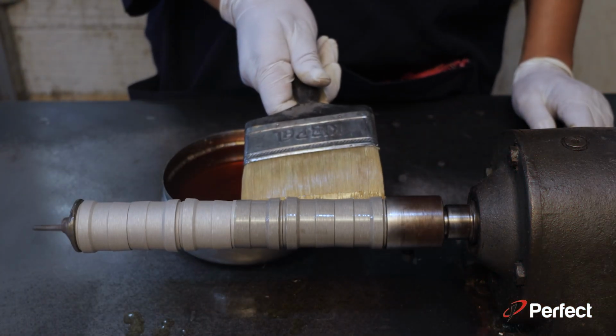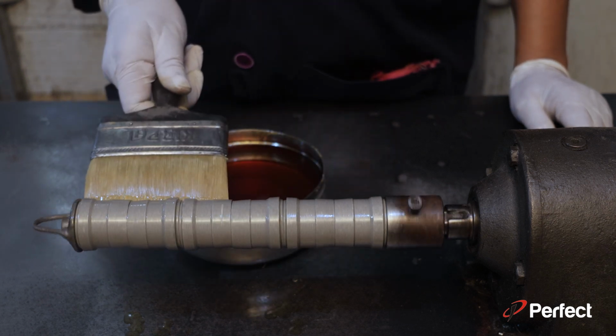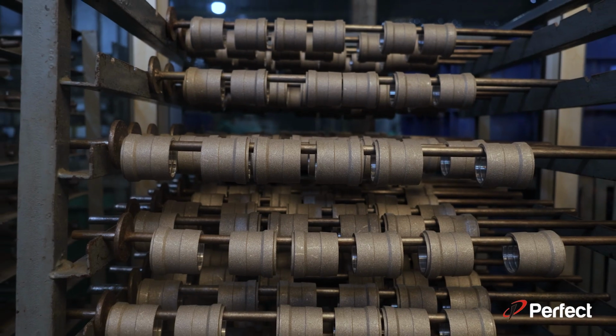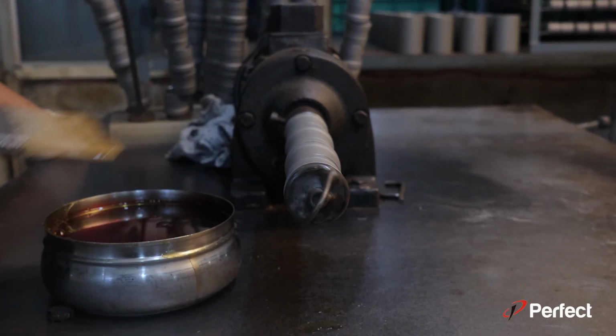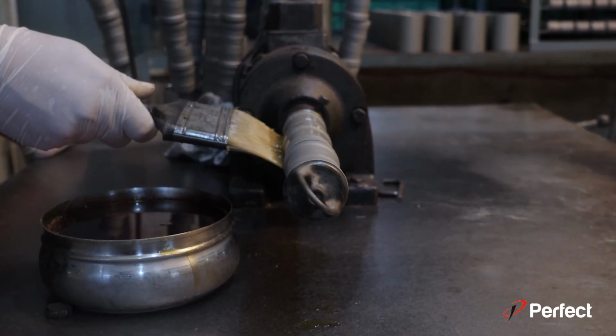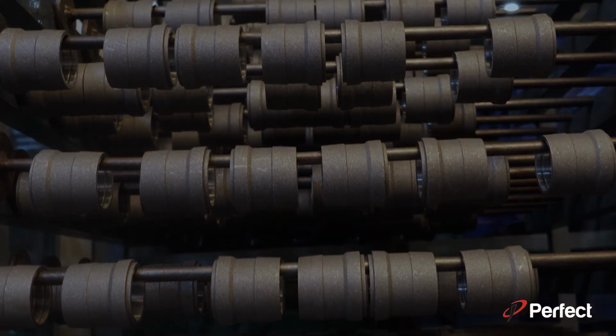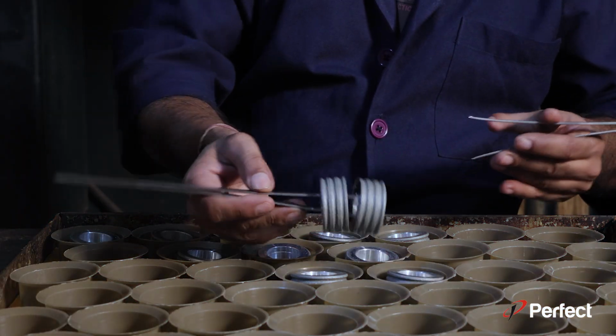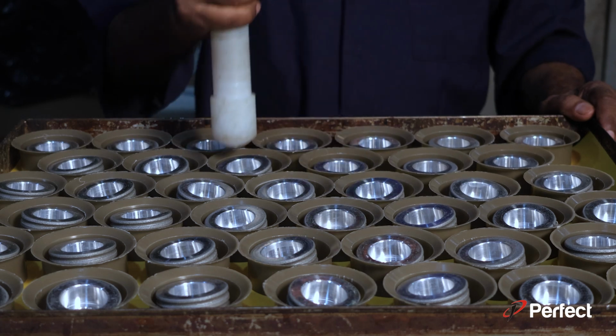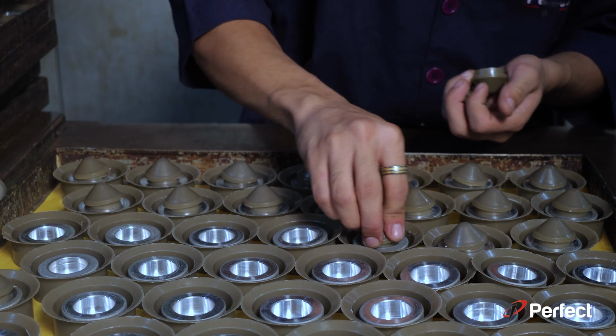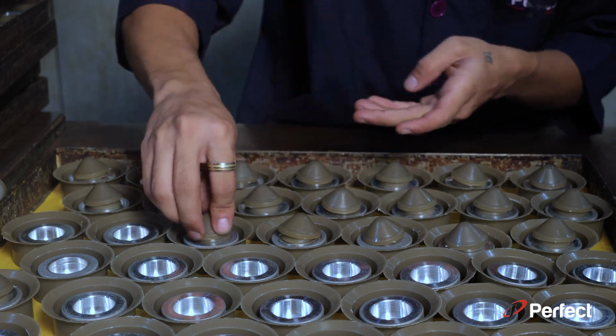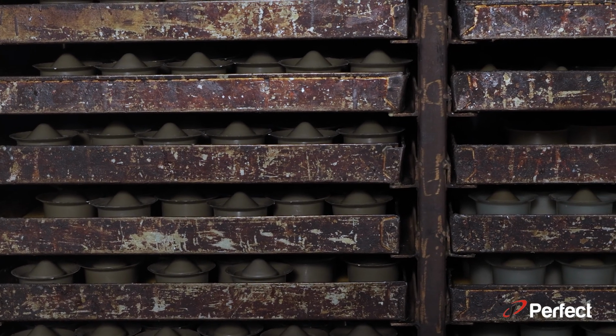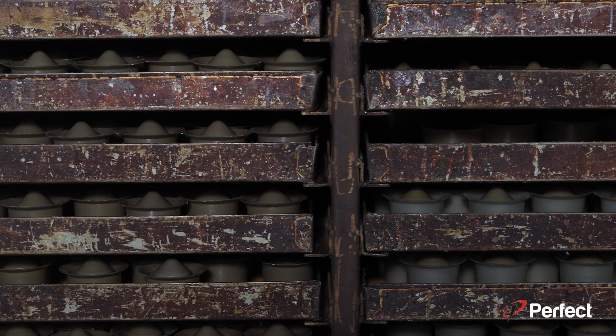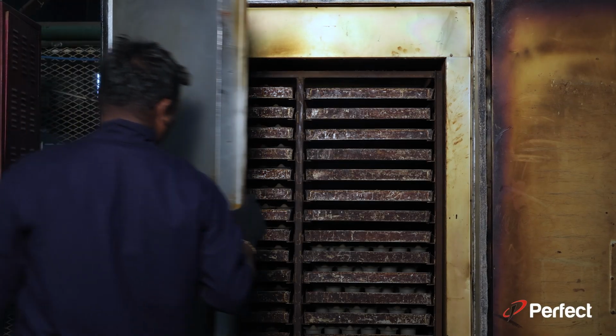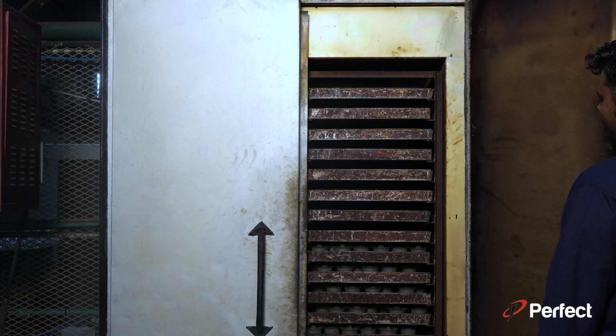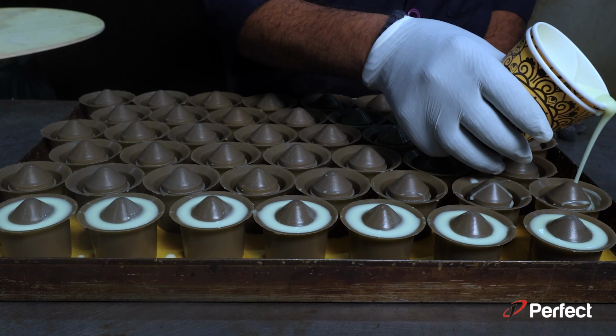Next, in a moisture-free room, adhesive is applied on the outer diameter of the inserts and they are left to rest for 1 hour. After this, a second coat of adhesive is applied over the first and left to dry overnight. Then, these adhesive-coated inserts are placed into polypropylene cup molds, forming a cavity for filling hot PU material around the inserts. The inserts, along with the molds, are then placed inside an oven and heated at 120 degrees Celsius for 2 hours in order to activate the adhesive and synchronize the temperature with the PU material.